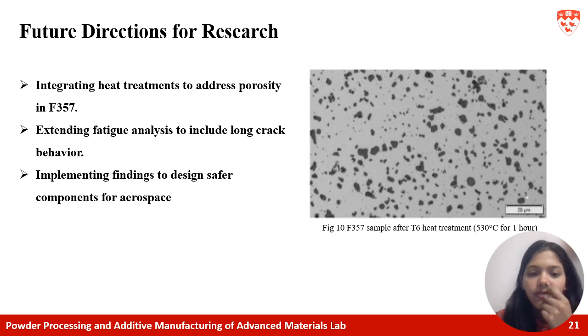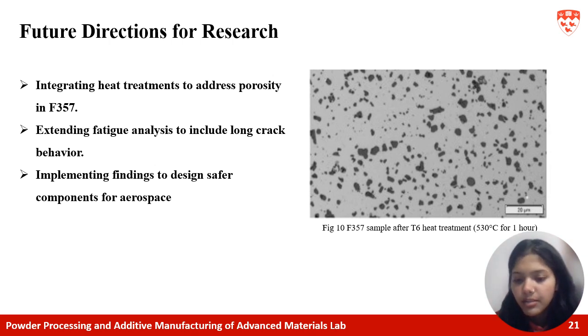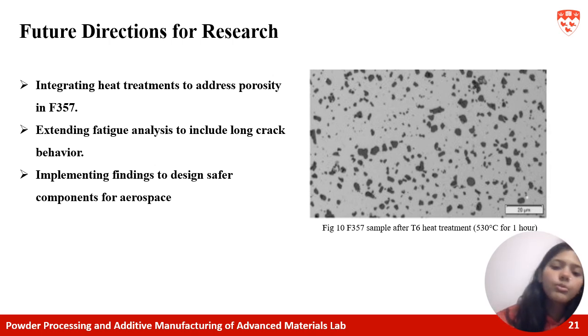So here is some of a test that we did recently. So to rather homogenize the microstructure, which we believed could mitigate the defects and remove or lower the porosity of the alloy, we did a T6 heat treatment, and we did a solution treatment at the high temperature of 530 degrees Celsius for 1 hour, followed by an aging at the rather lower temperature of around 160 degrees Celsius for 6 hours. And we see a rather homogeneous microstructure in the bulk and in the downskin.